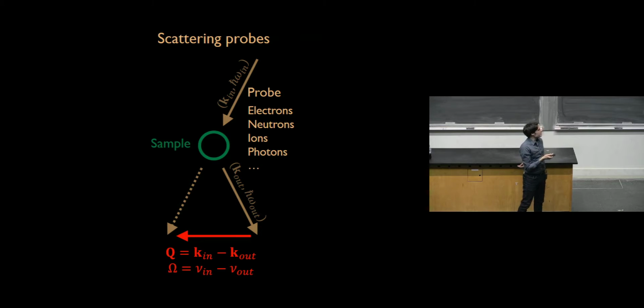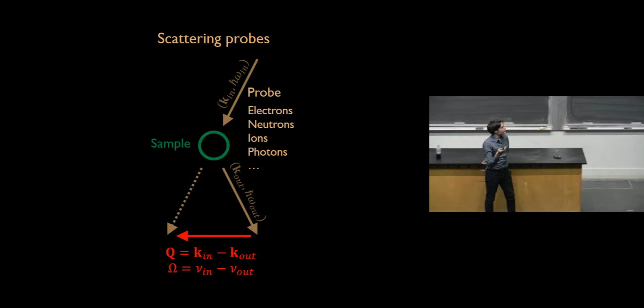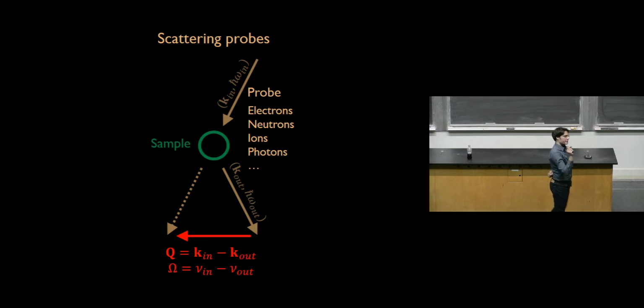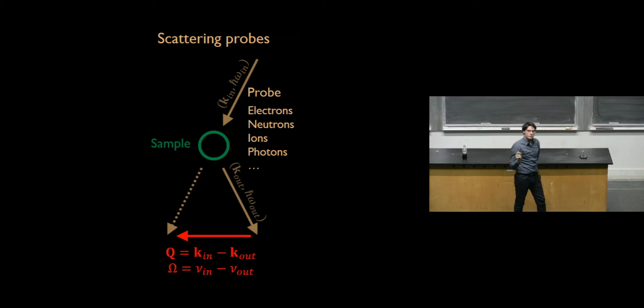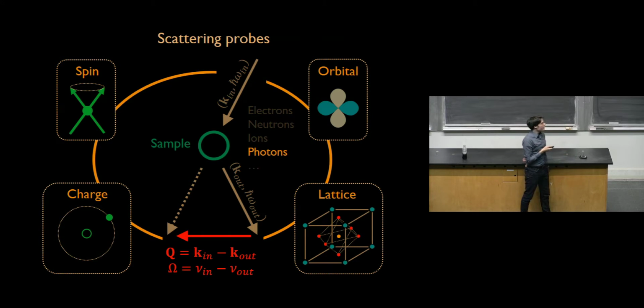A probe is anything that's willing to interact with your sample, so a lot of different particles can be used. And again, they have to carry a small amount of momentum in total. This is still a non-perturbative method of probing materials. So you can have electrons, neutrons, ions, or photons. Photons are the only ones that can measure charge, spin, and orbital degrees of freedom. Neutrons can measure spins very effectively. Electrons can measure the lattice or the charge very effectively, but the only ones that can probe all of these degrees of freedom really are photons.